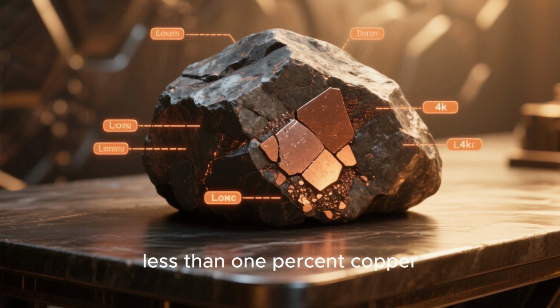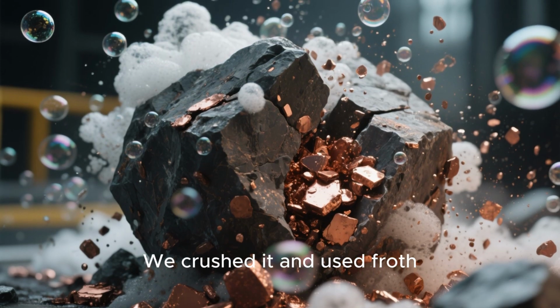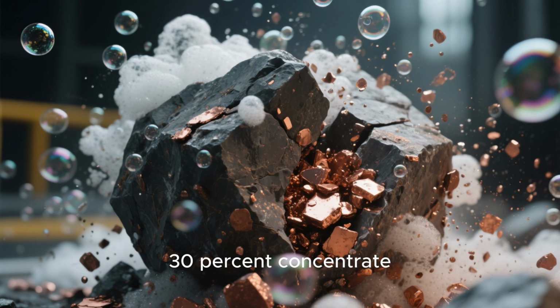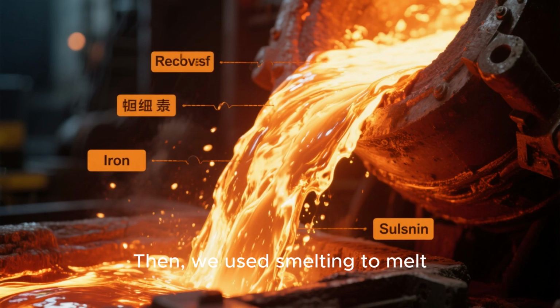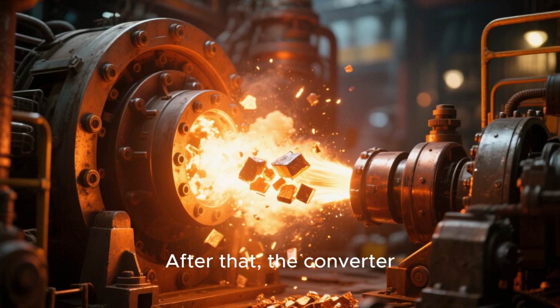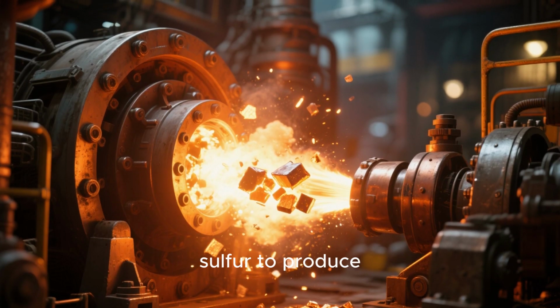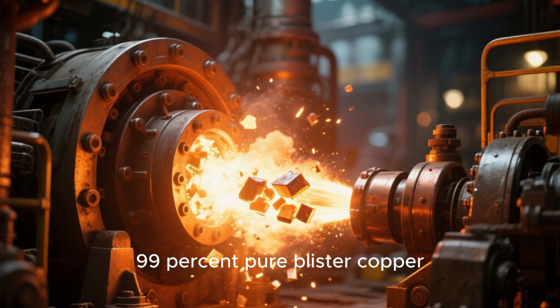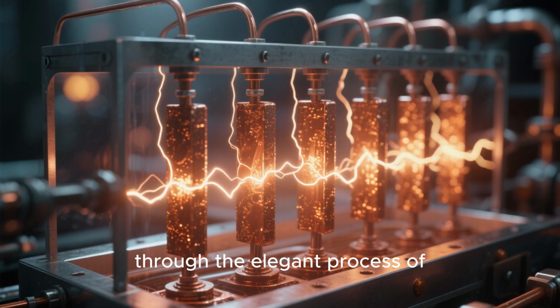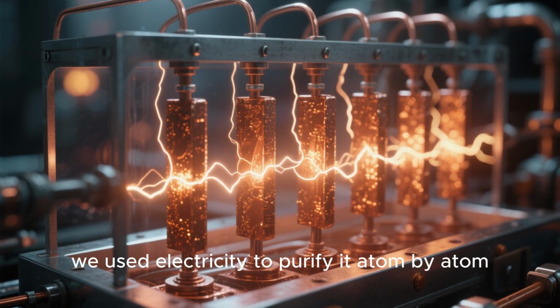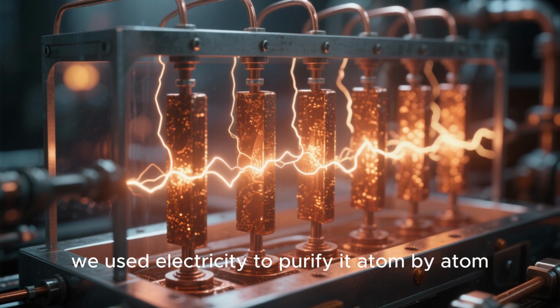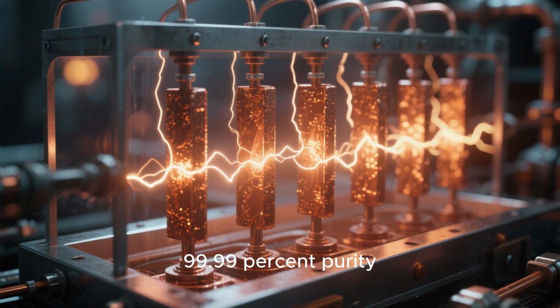So let's recap the amazing transformation. We started with a rock containing less than 1% copper. We crushed it and used froth flotation to create a 30% concentrate. Then, we used smelting to melt it down and remove most of the iron and sulfur, creating a 60% copper matte. After that, the converter blew out the remaining sulfur to produce 99% pure blister copper. And finally, through the elegant process of electrolysis, we used electricity to purify it atom by atom, reaching an incredible